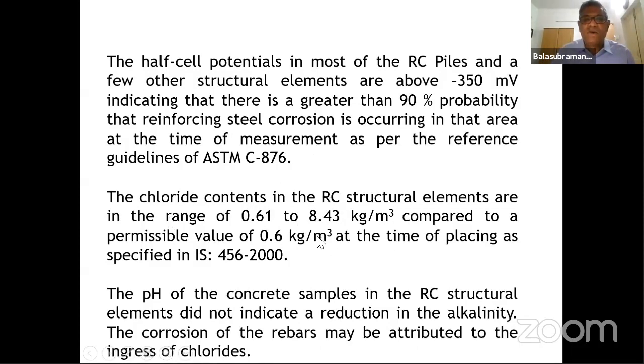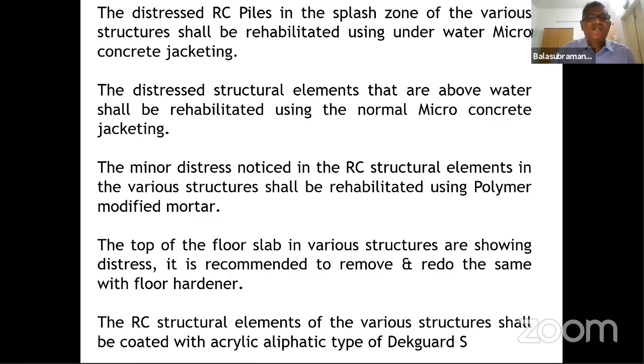Abnormally high chloride numbers, and the pH of the samples were quite okay. So the corrosion of the rebars is mainly due to chlorides. And the rehabilitation methodology we gave was: distressed RC piles in the splash zone, underwater microconcrete jacketing, and above the water level, microconcrete jacketing; minor distress with polymer modified mortar; top floor to be removed and then redone with a floor hardener. And then we gave a Dekguard, silane siloxane.